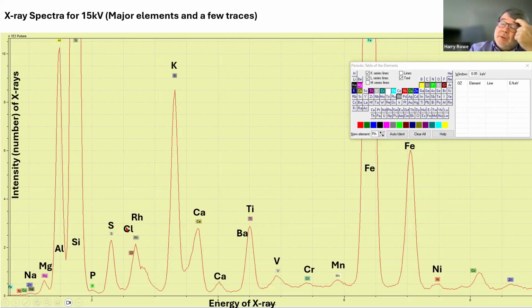Chlorine is another one. Everything that we drill out in the Permian and in the Williston is very high in brine, lots of chlorine. You need to get that salt out. Don't let it dry on the sample, because it will affect everything around this neighborhood. The rhodium is from the target. This is called the Compton peak, and we utilize this to normalize the spectrum. So messing with this by having a bunch of chlorine on it isn't good.